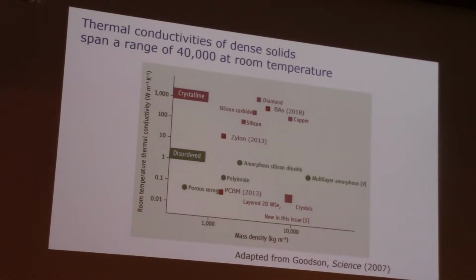So diamond has the highest thermal conductivity. I think graphene is maybe a little controversial, what exactly its value is at room temperature. It's not clear that it's much higher than that. But diamond has a very high thermal conductivity. The heat is carried by phonons, wave-like lattice vibrations. They have a high velocity and a high coherence, so they have a long mean free path. So they're very efficient at carrying heat.